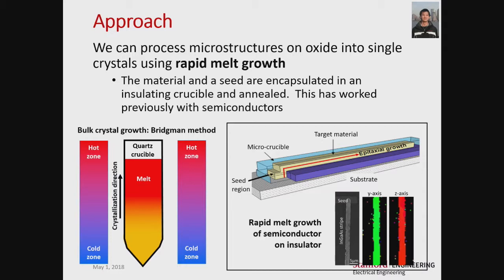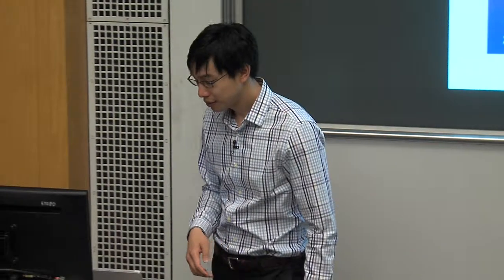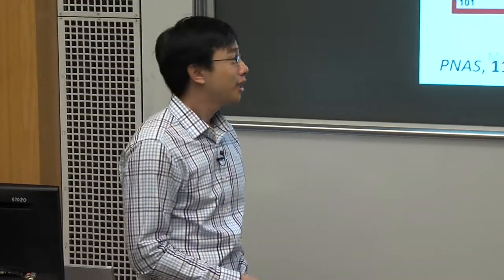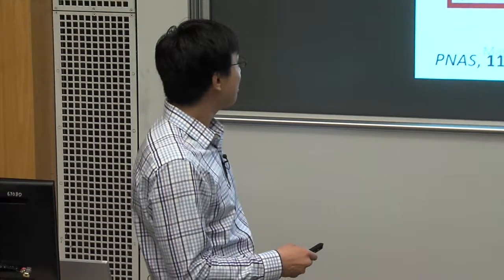This here is oxide. You encapsulate it in a microcrucible made out of oxide and melt it to the melting point of this material. What you ultimately get, due to surface energy considerations, is new crystal nucleation here and epitaxy growth in this direction. Here we can see, for indium gallium arsenide, a single crystal. These are EBSD, electron backscattering diffraction images of indium gallium arsenide on amorphous oxide. So the question was whether this could actually translate to metals. And the answer turns out to be yes.